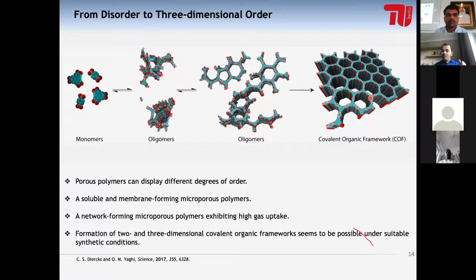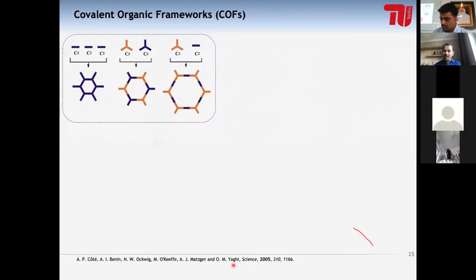So it is possible, if you put in a specific reaction condition, to synthesize materials which have perfect order in their backbone. And to do that, in 2005, the group of Professor Yaghi at the University of California thought that we can assemble different organic linkers which are C2 symmetric, or two organic linkers which are C3 symmetric, or one C3 and one C2 linker. We should ultimately get materials which should show the crystallinity as well as some